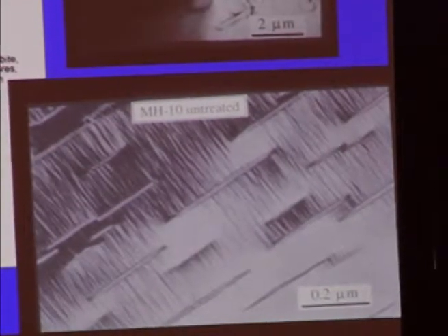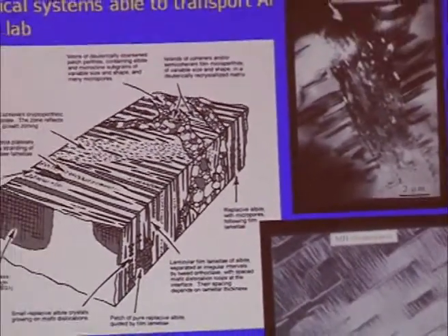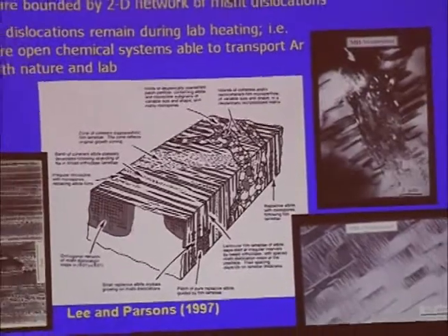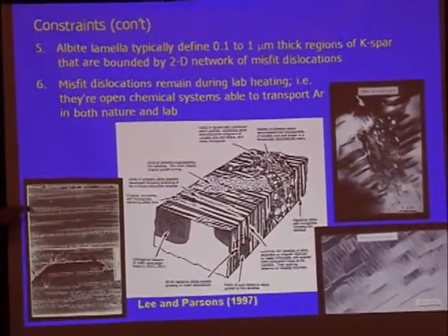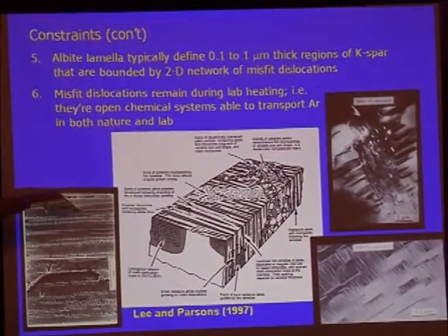And this, we argue, because in fact these things are occurring at the tenth of a micron. These albite lamella in the Tweed feldspar, they're creating a diffusion distance on the order of a few tenths of a micron. Well, that's about 1,000 times smaller than 100 or 200 microns, the biggest domain, and that sort of works for us. You can, in fact, decorate these things in HF vapor, and you'll see as you get to very small scales, they disappear.